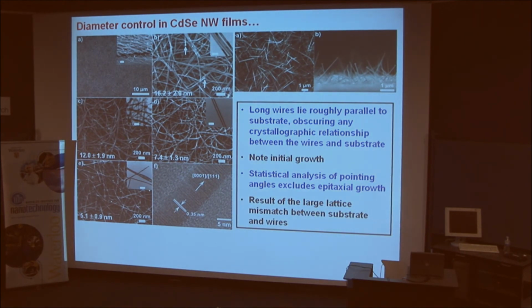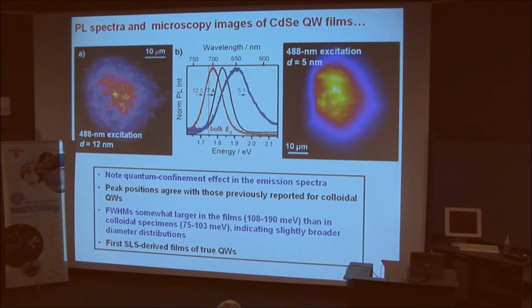wires. So here are wires that are 16 nanometers in diameter. And what does that say? 12 and 7 and 5, because we can control the size of the catalyst particle. And I'll show you in a moment that these, in fact, exhibit quantum confinement effects. Initially, the growth is not flat down on the substrate as these appear to be. They initially start growing upwards from the substrate, but eventually they get long enough that apparently they lie down. And if we analyze the pointing angles of these wires on our silicon 100, they're randomly oriented, indicating that these wires are not having an epitaxial relationship with the substrate. And that's probably because there's quite a large lattice mismatch here.